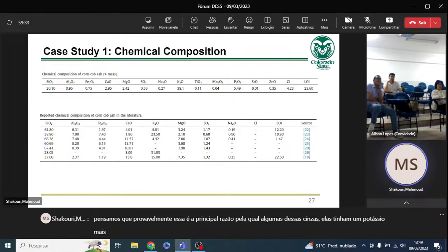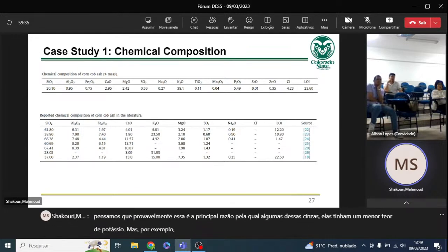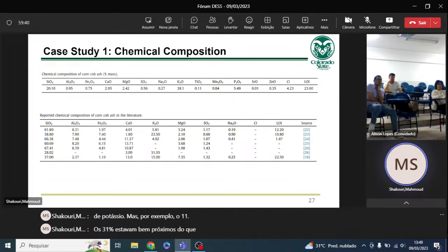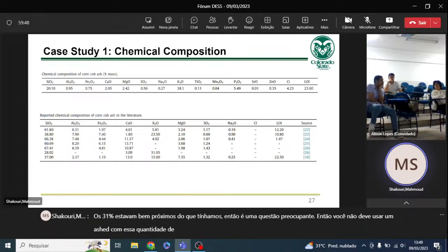But for example, the 31% was pretty close to what we had. So it's a concerning issue. So you should not use an ash with that amount of potassium or sodium because it will affect the properties